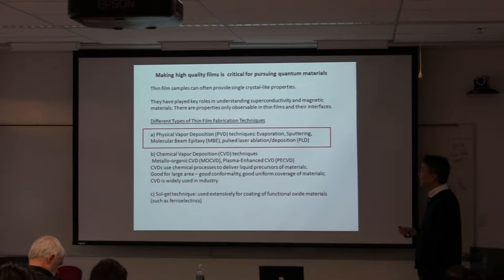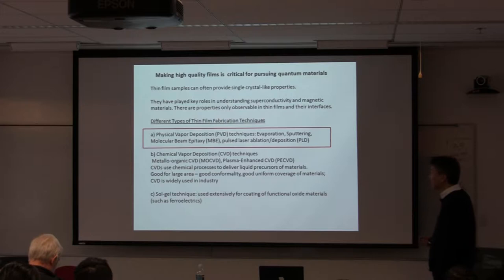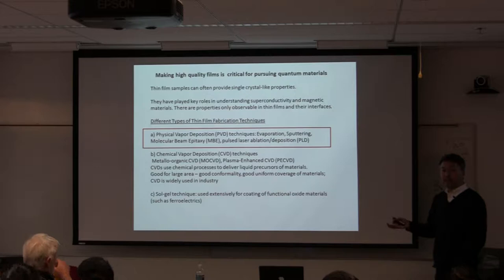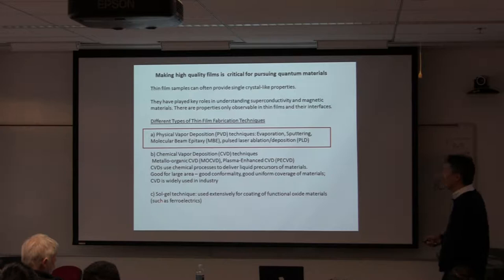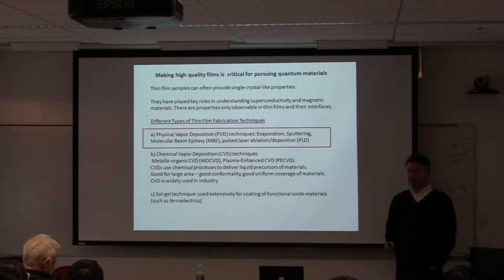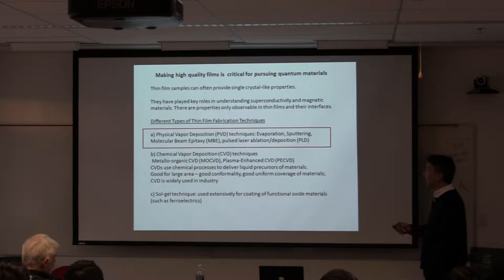CVD techniques are most commonly used in the electronic industry because they're good for making films with high conformality and large area deposition. However, for complex multi-component systems, CVD is not very useful. In the late 80s and early 90s, people tried to make YBCO superconductors with CVD, but after about 10 years gave up — it's just so difficult to control composition. Of course, these days 2D materials like graphene and TMDs are all done with CVD. There's also a sol-gel technique useful for making thicker, bulk-like piezoelectric thin films. But today I'll focus on PVD techniques.